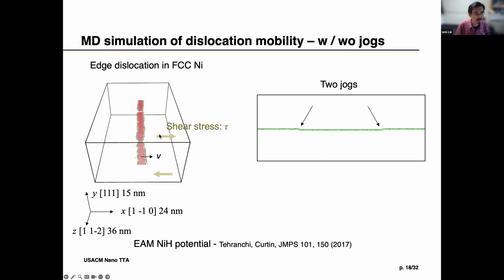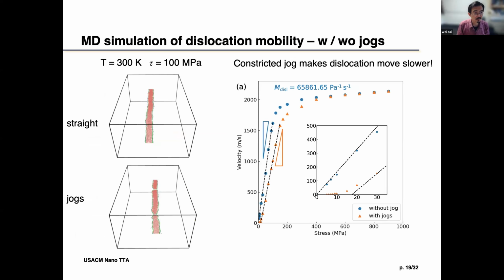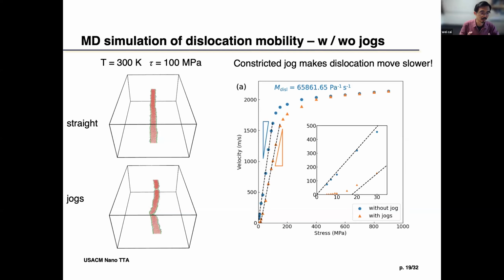And then this is the other one, in which you can see that the dislocation is over here, but then we introduce a pair of jogs. So the middle part goes down by one atomic plane, and then it goes up again to satisfy periodic boundary conditions. So it has a pair of jogs. And if you do this simulation at 300K, under the same stress, you can see that the one with the jog is moving slower. Because of that, the jog is dragging the dislocation. You can visibly see the dislocation is being pulled back by those jogs.